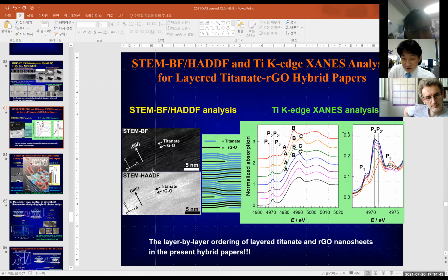So this is the spectra. This is quite different from the powder pattern. It is highly anisotropic. Such a spectral feature is obtained from a highly oriented deposited film. From that we can get some information on the orientation of the nanosheet. Also, by using the grazing angle mode, I believe that we can probe the out-of-plane bonding nature. Actually, I have experience with this kind of angle-dependent XAS analysis.